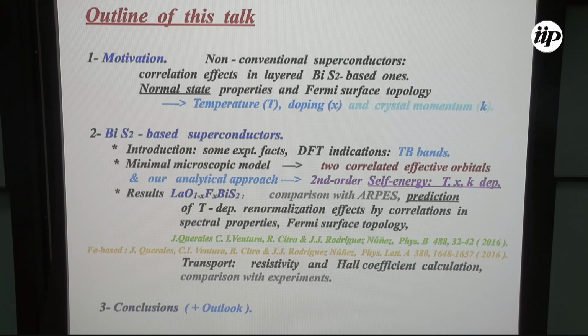With our approach, which is based on using two correlated effective orbitals and a treatment for these correlations, which are intermediate in these materials, we can obtain a second order in perturbation correlation self-energy, which has temperature, doping, and k dependence. That's interesting because we can describe spectral properties like the spectral density function as a function of k, and that's what we already published in this paper, shown there in green. Today I'm also going to show you the newest transport results, and then I will conclude and tell you our outlook.